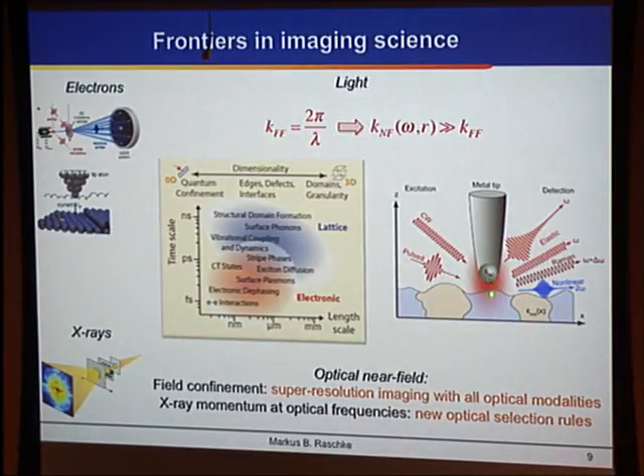When you have this nanoprobe, it is this spatially confined and momentum-space increased field which is responsible for the high spatial resolution, which requires that you scan this tip in very close proximity to the sample, on the order of the dimension of its radius. And it is this radius which provides a metric for the momentum, because the inverse of the tip radius gives the corresponding increase into the regime of high momentum states. With a few nanometer apex radius, which you can make with metallic tips that perform as an optical antenna, you actually get X-ray momenta at optical frequencies.